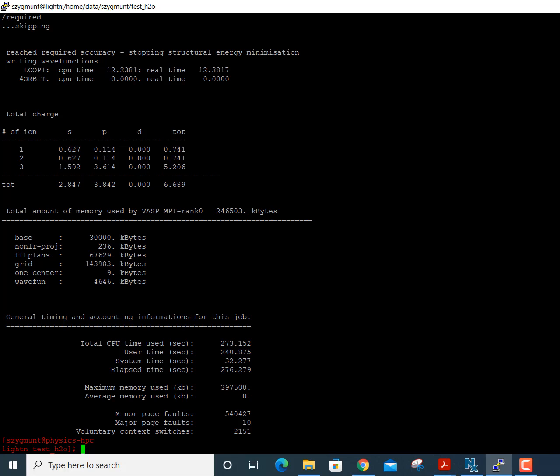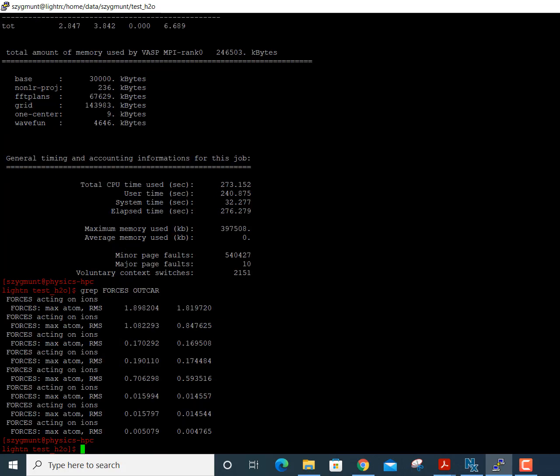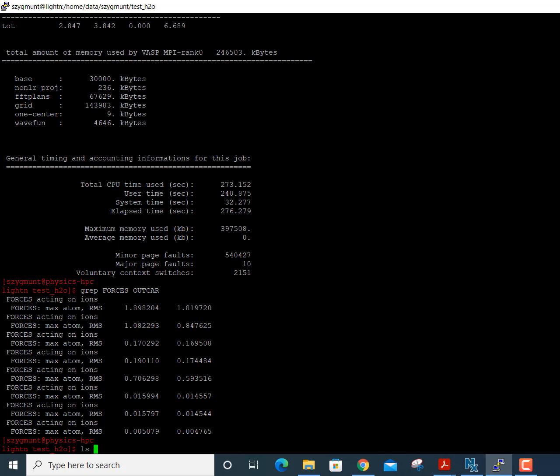You can also use the grep command to search for the string 'forces' in the OUTCAR file: 'grep forces OUTCAR'. This shows, for each of the ionic iterations, the maximum force on any atom and the root mean square (RMS) of all forces — labeled 'forces max atom' and 'RMS'. At the very last iteration, both values fall below 0.01 eV/Å. In the previous iteration they were 0.015 and 0.014, which is above the EDIFFG threshold of 1E-2 (0.01) set in INCAR — confirming convergence is achieved in the final step.